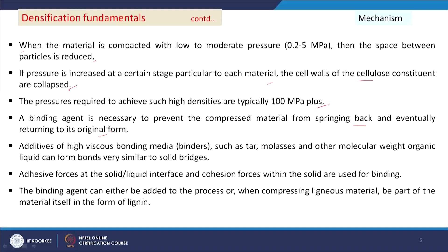Without binders at low pressure, particles may be compressed but spring back. Additives of highly viscous bonding media such as tar, molasses, and other high molecular weight organic liquids can form bonds very similar to solid bridges. Adhesive forces at solid-liquid interfaces and cohesion forces within the solid are used for binding. The binding agent can be added to the process or, when compressing ligneous material, it can be part of the material itself in the form of lignin released under very high pressure.